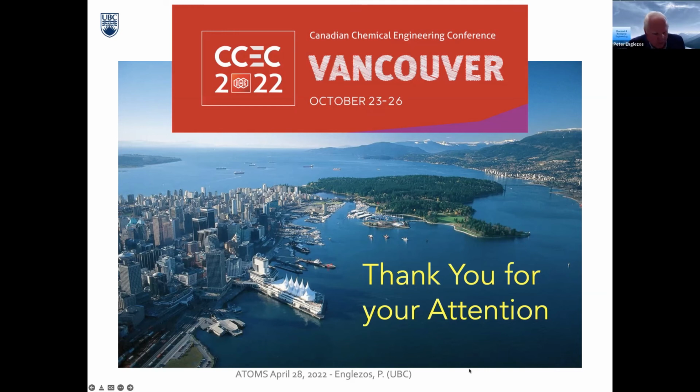Yeah, in both cases we've published the sample holder and we've given a picture and a description of the dimensions of the sample holder. The samples in the calorimeter are quite small. I forget the exact volume, but they're good enough because this high pressure calorimeter is quite sensitive, and you can obviously calibrate it against known specimens. With the rheometry, it's really macroscopic, the experiment, and what happens is the apparent viscosity shoots up once you have hydrate crystals, and you have to be really careful and stop it. You don't want to damage the rheometer. So we didn't have a problem with actually getting a signal.